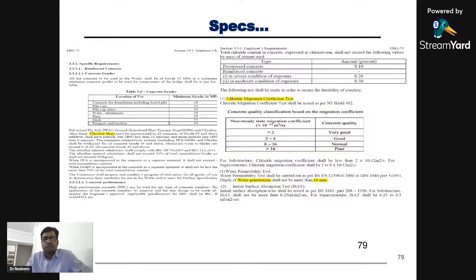For the substructure, their requirement was a coefficient of less than 2 into 10 raised to minus 12 meter square per second. That was in the specification for the substructure. For the superstructure, the specification was 2 to 8, meaning good. Water permeability in the specification was less than 10 mm, and ISAT was specified at 0.25 ml per square meter per second. These were the durability specifications for that project, and they are being achieved.